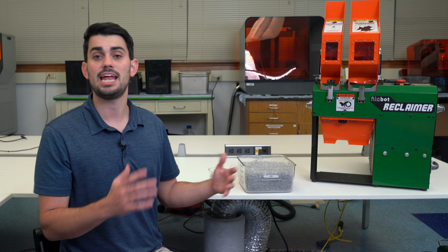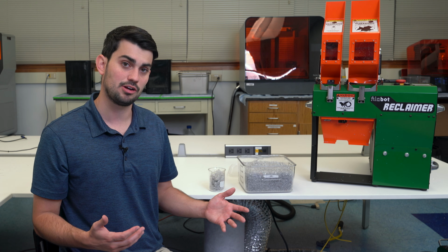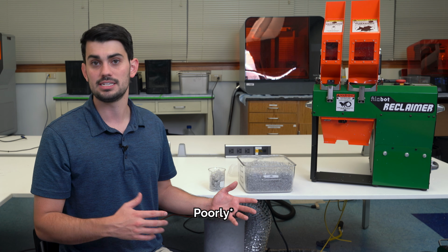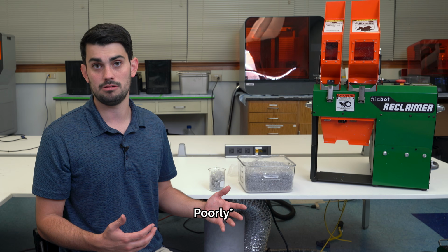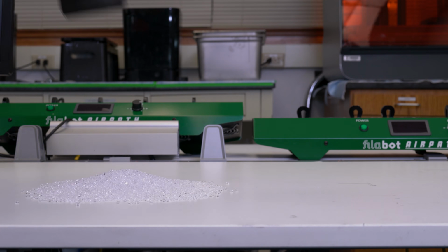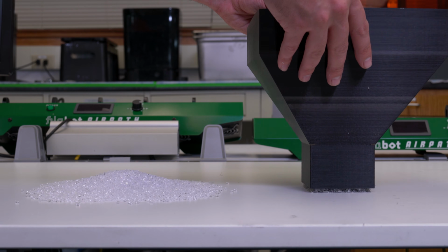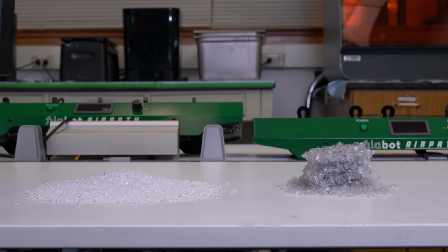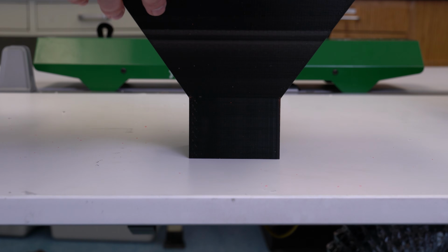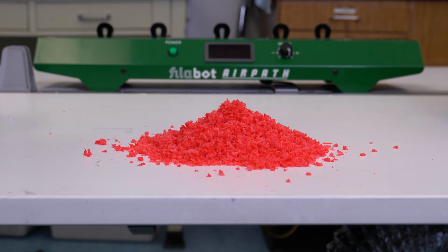Free-flowing materials have an angle of repose less than 45 degrees, with poorly flowing materials having a larger than 45-degree angle. Here you can see that new PET pellets are highly flowable, with them spreading out to almost a single pellet layer, creating a very low angle of repose. The PET regrind, on the other hand, couldn't have performed any worse. It moved very little once the funnel was lifted. It has almost a 90-degree angle of repose. And for your reference, here is a 3D printed regrind from the first part of this video.